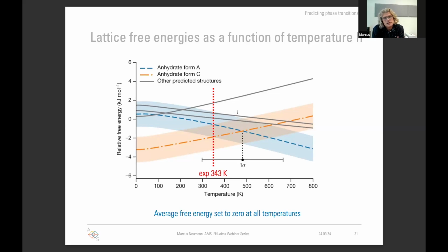Experimentalists easily measure phase transition temperatures to within a Kelvin. And that means that to get to experimental accuracy, our energy calculations have to become a factor of 100 better. So be my guest, feel invited to try and to improve the method. The data is there. You can test that you are doing better.